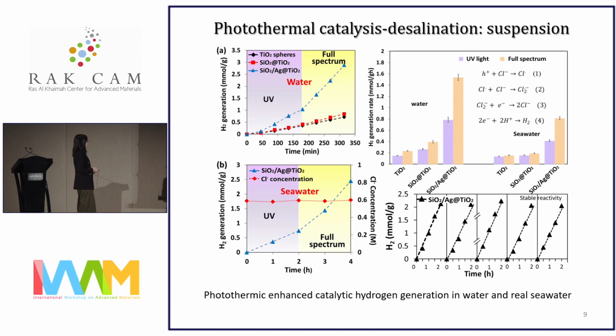Then the photothermal enhanced catalytic hydrogen generation can be observed for both water as well as seawater. And the hydrogen generation for seawater is consistently lower than that of water. And the reason for that is because of the formation of chlorine radicals due to hole oxidation, which the chlorine would then be reduced by the photogenerated electrons, and this creates an electron pathway that competes with the photocatalytic hydrogen reaction. Notably, the chlorine ions concentration remains unchanged with time, and this is very significant because basically it alleviates the concern of producing a toxic gas or acid in our system.